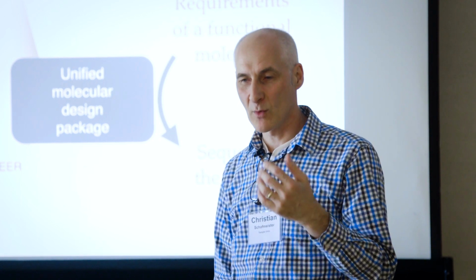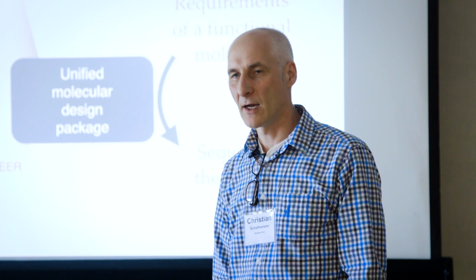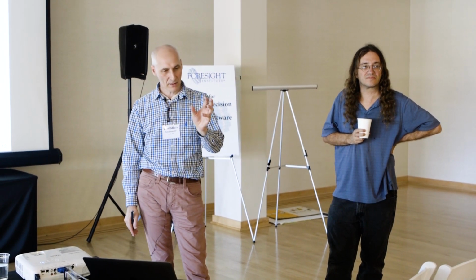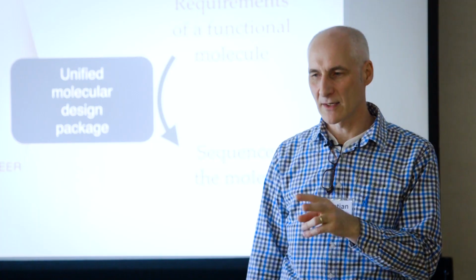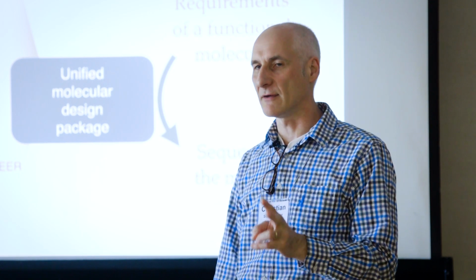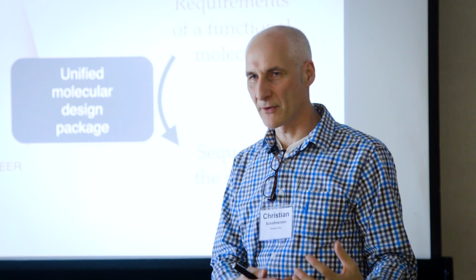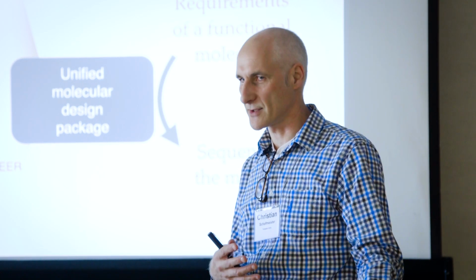What the Department of Defense wants, what DTRA wants, are abiotic, non-natural approaches to hydrolyzing nerve agents. And we've got a couple of ideas on how to do that. One is mimicking some enzymes that hydrolyze nerve agents. Another is taking the zirconium oxo cluster that the Hupp group at Northwestern has demonstrated in metal organic frameworks, which is very active, and turning it into a soluble form, because you can't inject MOFs into people. They're crystals. You don't want to inject that into someone's bloodstream. But a soluble form that's 3-4 kilodaltons in size would be very, very useful.